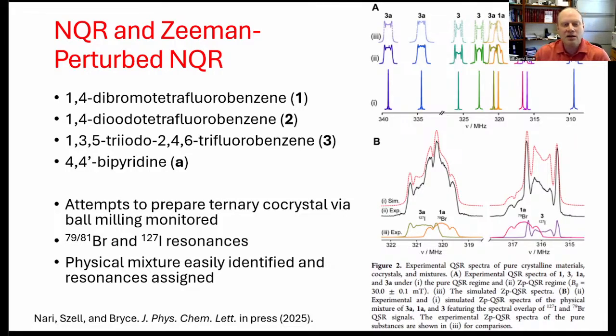So again, our perfluorinated iodobenzene, perfluorinated dibromobenzene, and a bipyridine donor molecule. So we've got iodines and bromines in these molecules. We're trying to form cocrystals with mechanochemistry and monitor what's happening. So what we found was that we didn't get our ternary cocrystal. We actually got a mixture, an impure mixture, or a physical mixture of things.